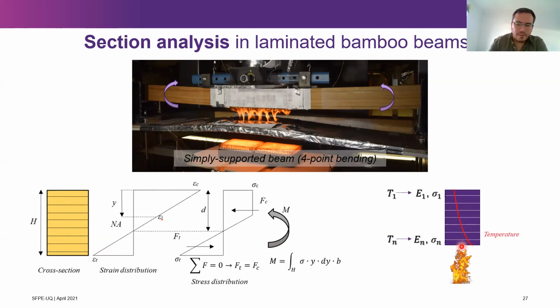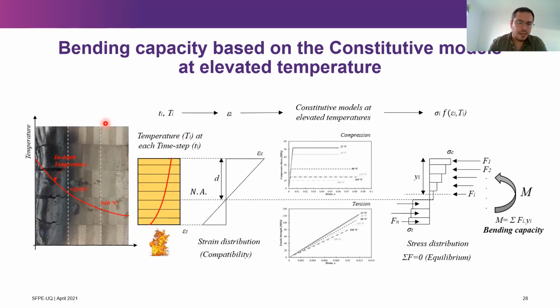So each fiber in our cross section is going to have a different mechanical property, because this is what we found in the first part of the PhD, that the mechanical properties were changing in function of that internal temperature. So what we proposed basically was to use the same section analysis, but changing the mechanical properties of each fiber. So you can divide that cross section in as many layers as you want. You will assign those stress strain models for each of the fibers, and obviously you apply again structural equations, like equilibrium equations, to obtain the bending capacity.